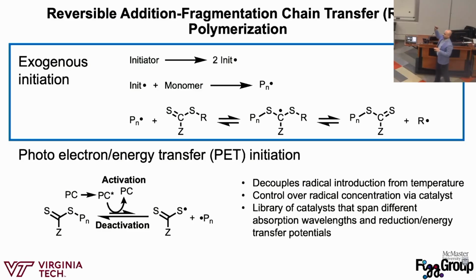So we don't have to have an initiator that goes to that initial chain transfer process to initiate our chains. We're just relying on the photocatalyst to react with the chain ends and have some sort of activation, deactivation. Those chains can also do the hot potato mechanism. They're not kept away from doing that. We're just introducing the radicals in a different pathway.